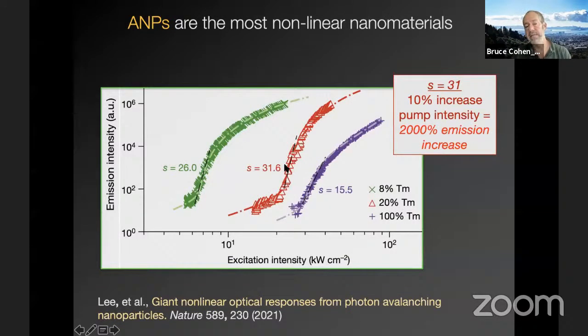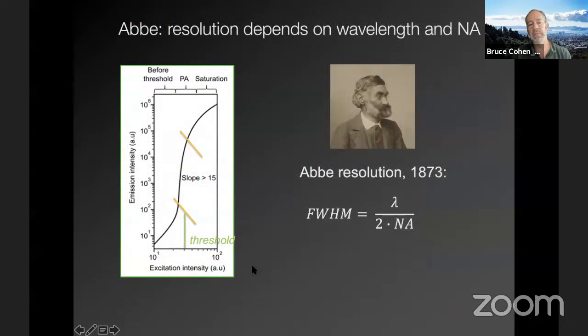And what that means is if you're in this part of the curve, if you have kind of standard imaging, you turn your laser up 10% and you're in a linear part of that spectrum, you expect a 10% increase in emission. If it's a 2 photon event, you might expect around a 20% increase in emission. Here, for this sort of level of extreme nonlinearity, a 10% increase in our pump power gives us about a 2,000% fold increase in emission.